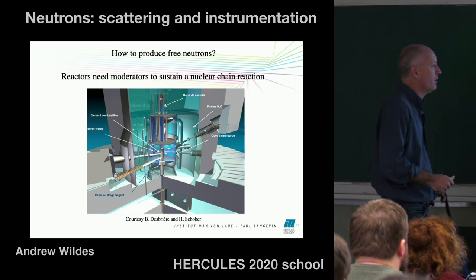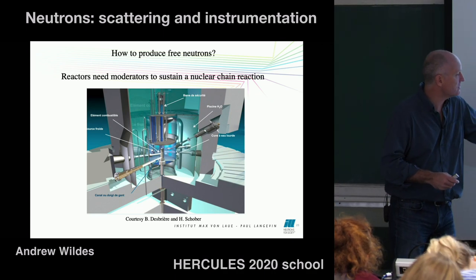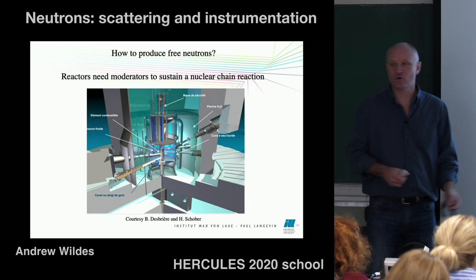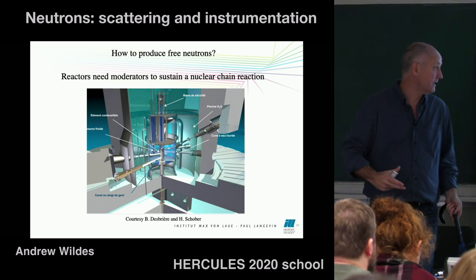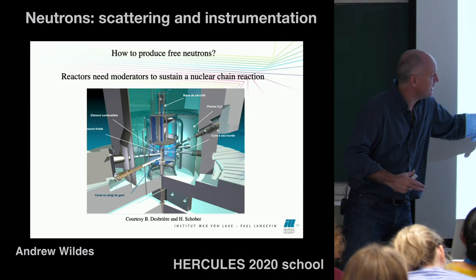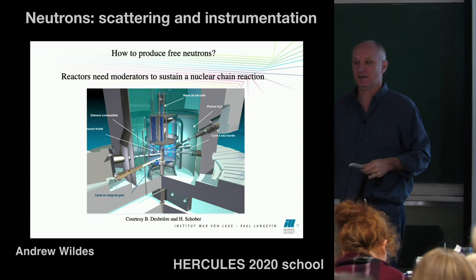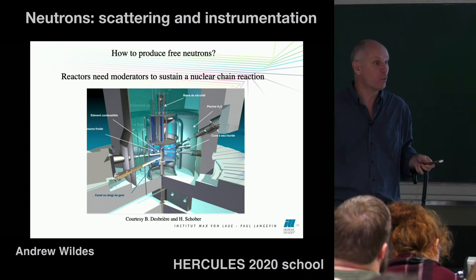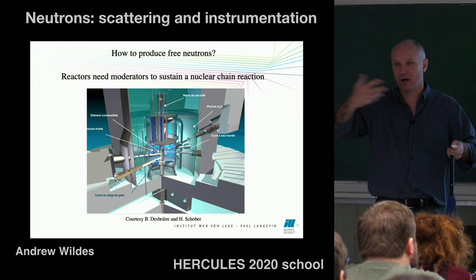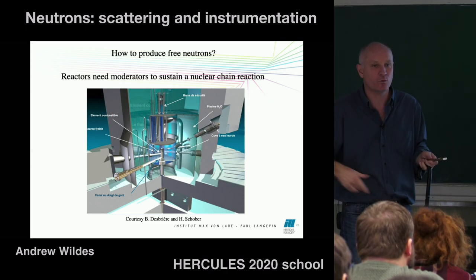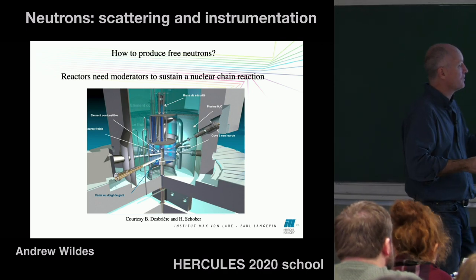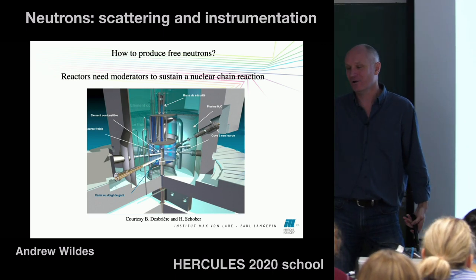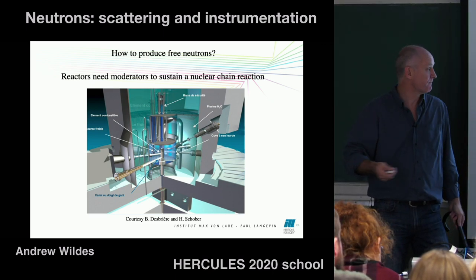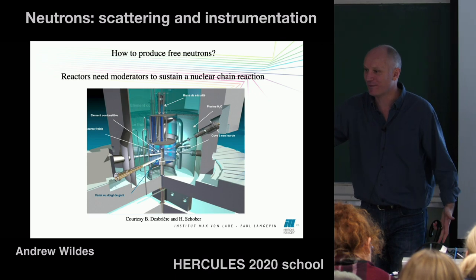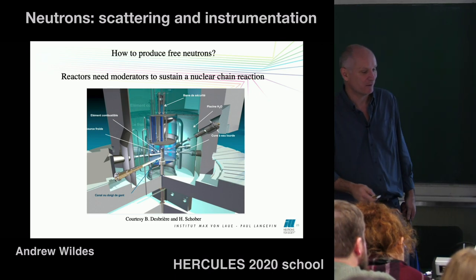And here's a cut through from the ILL. In the center here, this part here, that's your fuel element. That's where your uranium actually is. And it sits inside this container here. The container is full of deuterated water. And the neutrons that come out very high energy, they rattle around in this deuterated water, they lose energy. They then are able to interact again with the uranium to produce the next fission process. And some of them will come out and you'll be able to put them in your instrument.